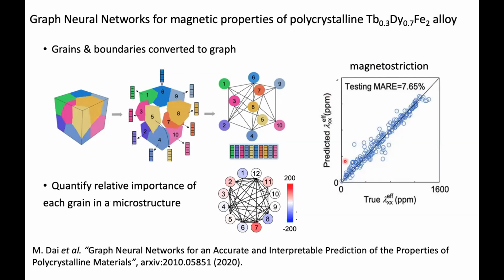And the property of these complex microstructures, such as magnetostriction, were fitted to a graph neural network, and they were fairly accurately reproduced. And very interestingly, similar to the PageRank web page ranking of Google, you can quantify the relative importance of each grain in the microstructure. So here, the red grain is a grain that has much more significant effects on the magnetic properties of the system compared to the white or blue grain. So such relative importance is essentially impossible to discover without knowing the interconnectedness of individual grains.